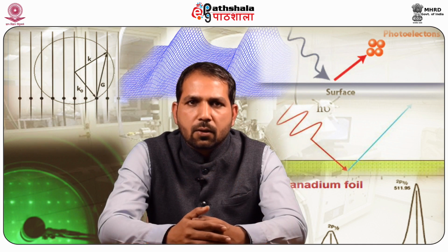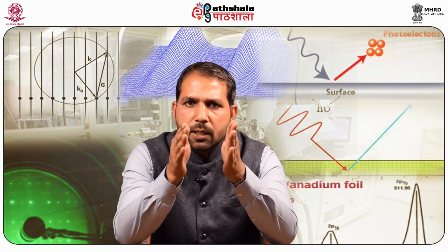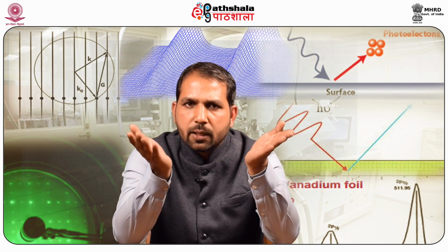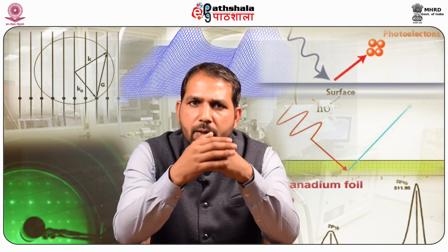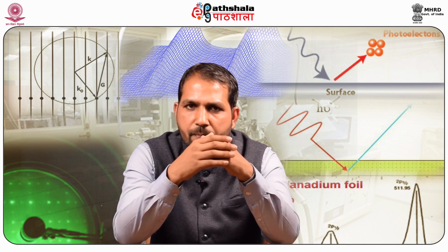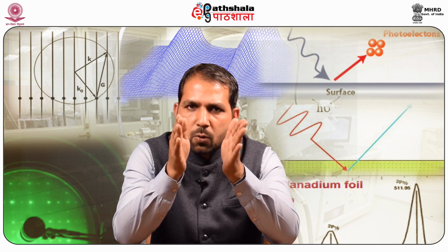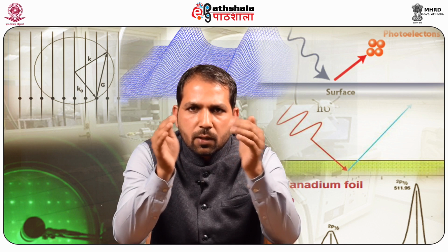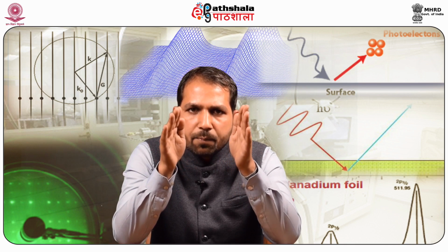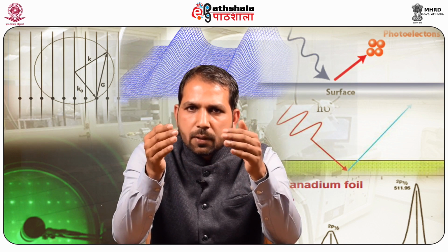Preparation of electrodes. Typical preparation of a microscale electrode is performed by heat sealing a microwire or carbon fiber in a glass capillary under vacuum. This tip can be connected to a larger copper electrode using silver epoxy, then polished to yield a sharp open tip.